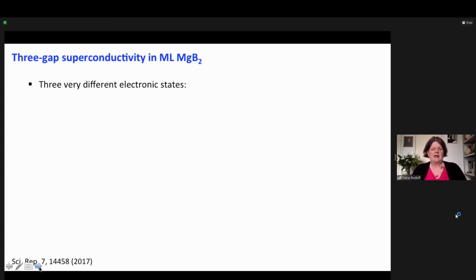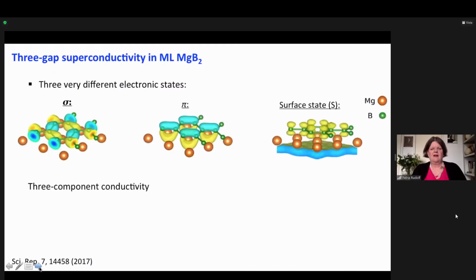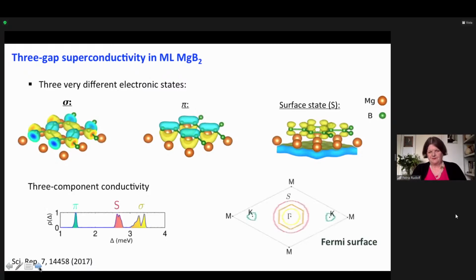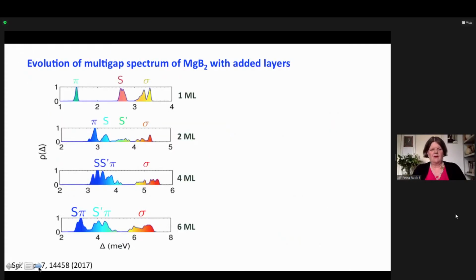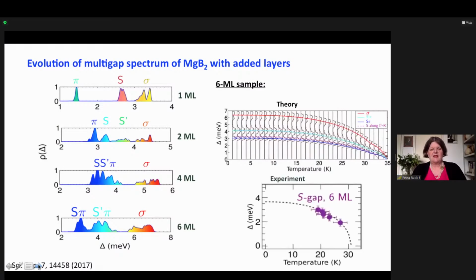So what he did is to look at the 3 different electronic states and to calculate this 3-component conductivity, and to look how it varies. So you have the surface state and you have the sigma and the pi electrons. And he looked how it varies with thickness. And we were very, very happy to see that his predictions go very well with what we found experimentally.